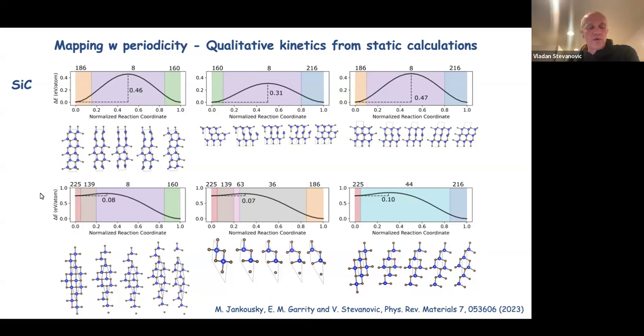There is another thing that we noticed from this plot: rock salt somehow transforms quickly into any of these three, rhombohedral, wurtzite, and zinc blende. So we asked a broader question about rock salts in general. If this can be generalized, this rock salt transforming quickly into the others, then even if you were to shift the energy, and let's say you make a rock salt ground state and an excited state or higher energy state, this geometric transformation would remain the same, and the barrier likely would remain low. So the question was really, if we investigate all the rock salts, so all the systems with the rock salt ground state, do we find polymorphs?